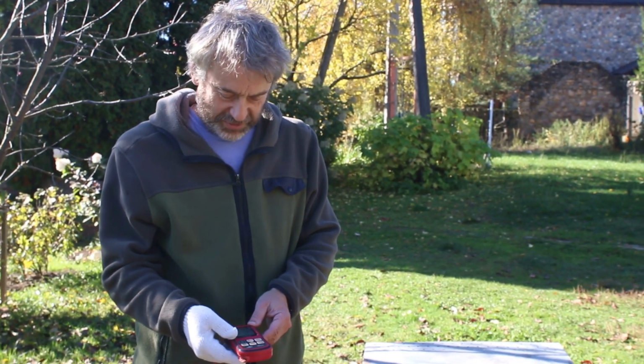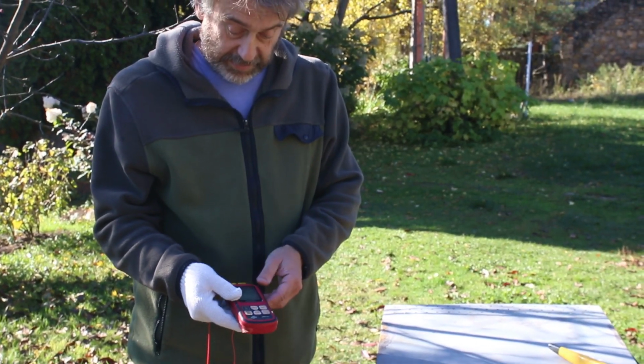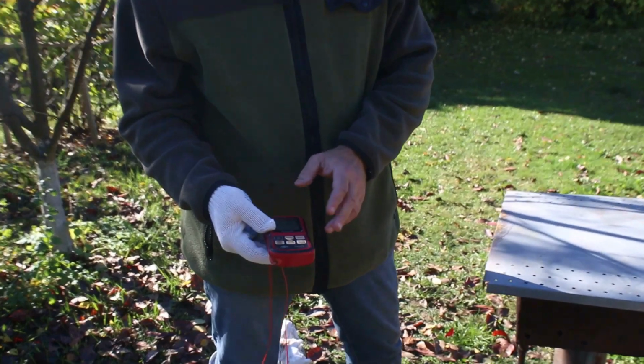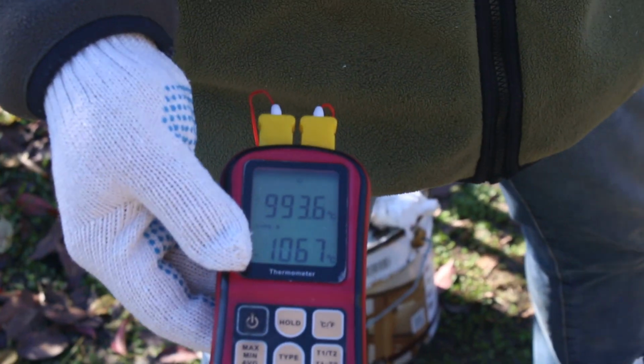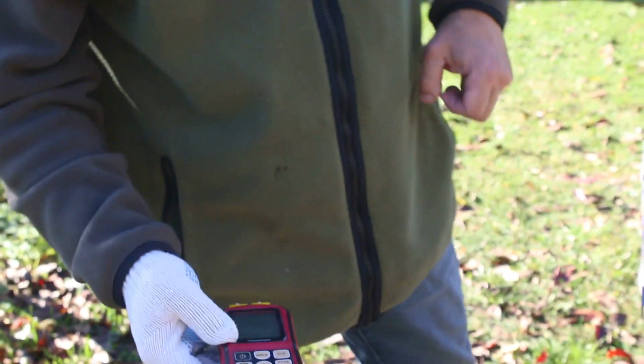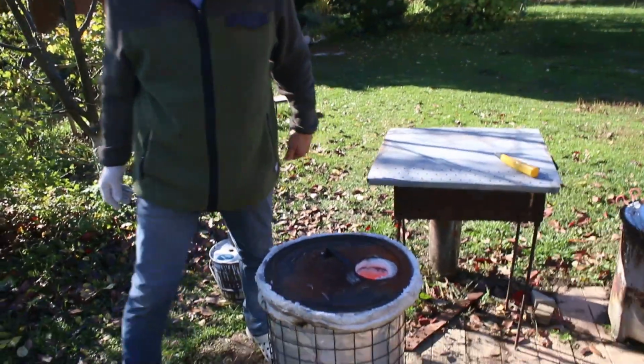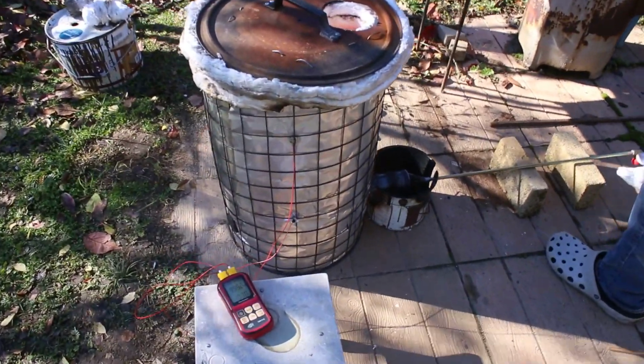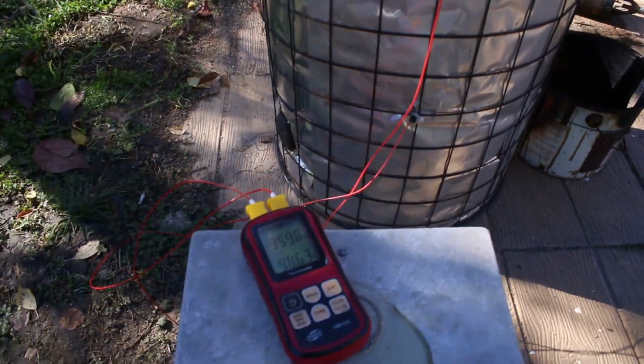Okay, about an hour and a half, about 2 hours passed. Let's look at the readings. It's about 1070 at the bottom of the kiln where the fire enters, and about 990 at the top. So the difference is like 70-80 degrees, which is normal, but it's not necessary to fire that high. But we need to keep in mind that as soon as we turn off the burner, the temperature drops like 100-150 degrees, and also it's not cone. For this firing I didn't use cones, so by cone it will be lower if we measure with cones. Also, with this type of lustre firing, I think it is better to overfire than underfire. That's what I think.